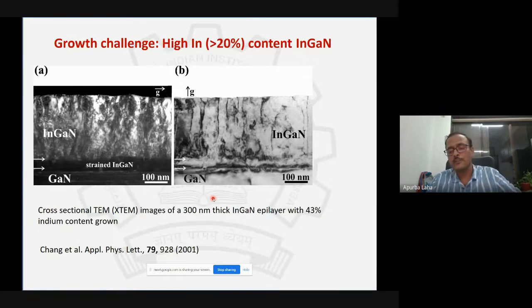So one of the reasons we have the green gap is that, as we have seen in the previous case where aluminum incorporation was challenging, the indium incorporation is also very challenging. If you want visible light, as I said, indium nitride has a band gap of 0.6 electron volt. Gallium nitride has 3.4 electron volt, which in turn gives you emissions in the range of 365 to 370 nanometer. So if you need visible light, which is 400 nanometer and above, then you need to add indium into it.